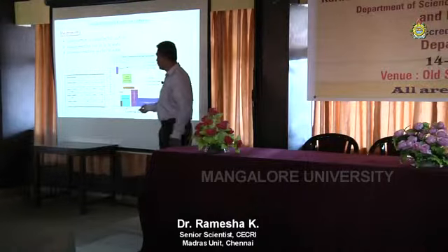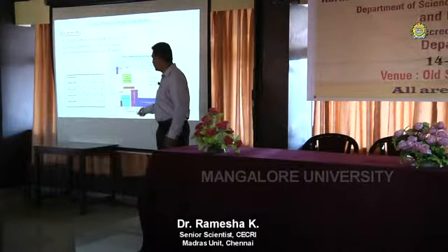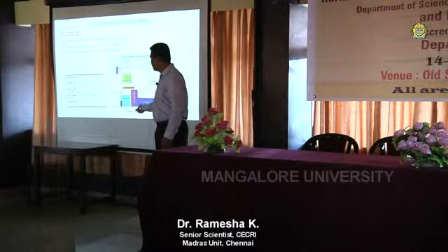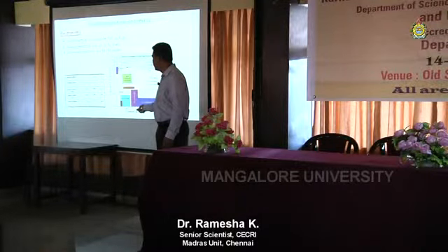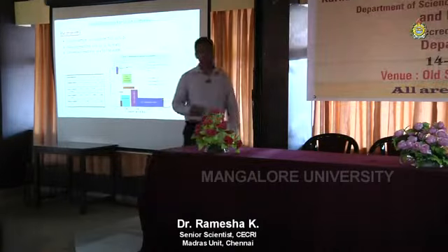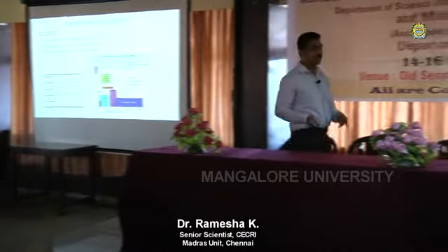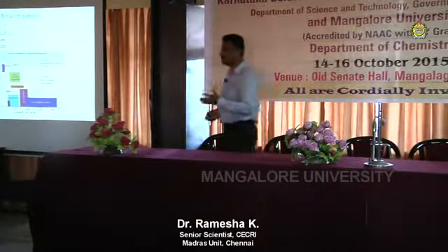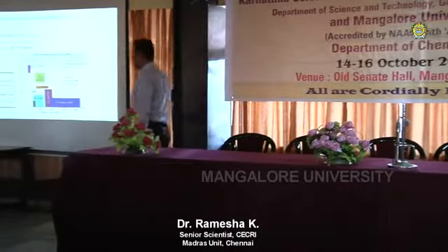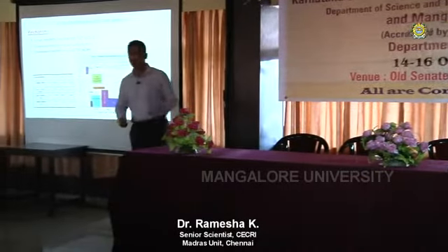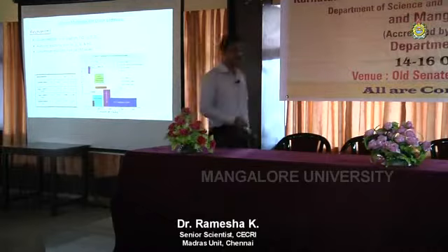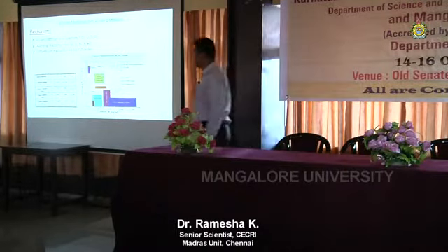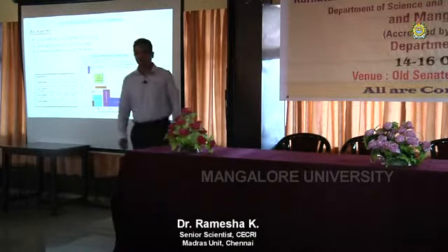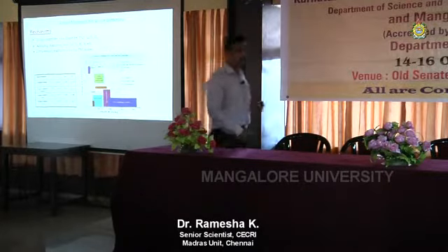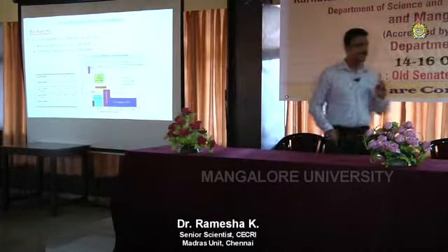Because of that, you have high capacity, theoretical as well as experimental. So the capacity value is actually much higher than the intercalation reaction, right? But everything looks good, so why don't we use silicon then? The problem is the volume change. When it forms an alloy, the volume changes by 300%.